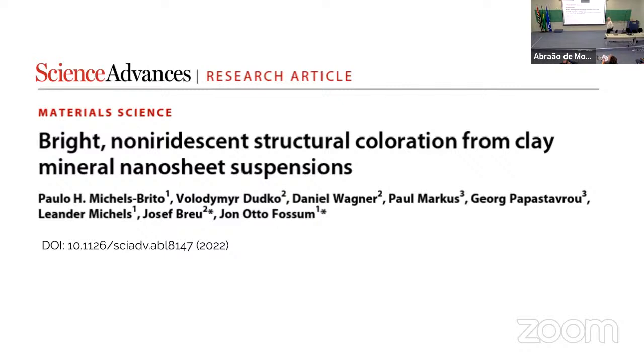20 minutes left, okay. This is another issue which seemingly is very different, but it's the same. And it has to do with how we play around with the clay at the nanoscale. We do the same game in this case as we did with the CO2. So this is a paper we published this year, and it's about structural coloration using clays. For the CO2 capture, we work in the crystalline swelling regime. In this case, we work in the osmotic swelling regime and the nematic phases in suspension.